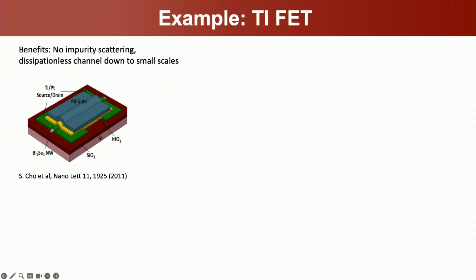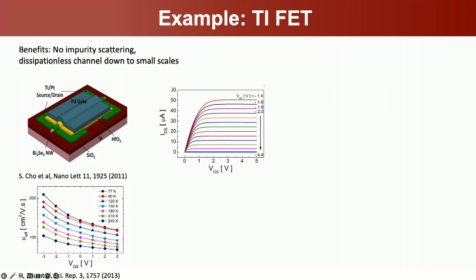So if you just took a really simple configuration and tried to make an FET out of topological materials, what do you see? You see curves that look like this. These are transfer curves, as ECE people call them. And actually, this looks very similar to what you'd expect for a silicon transistor. It has sort of linear behavior, and then it saturates at high voltages. And you can also measure the mobility as a function of voltage, and you can say that, to first extent, it looks like a transistor.